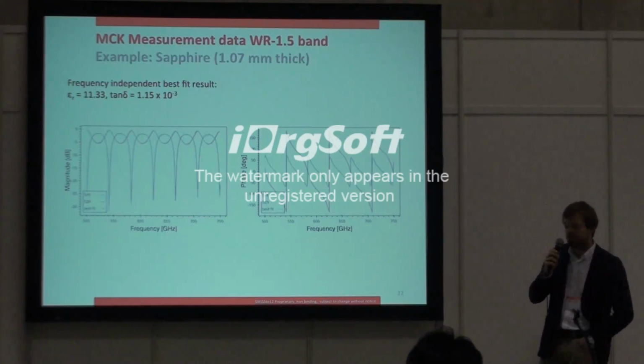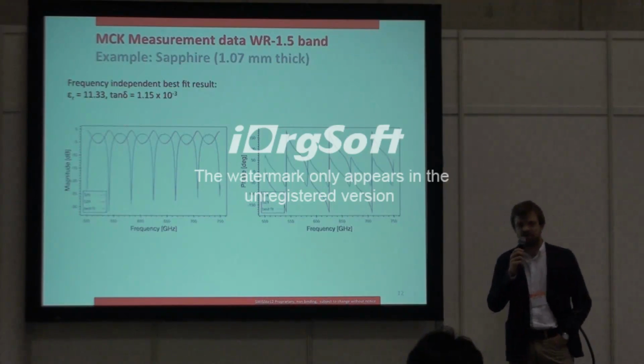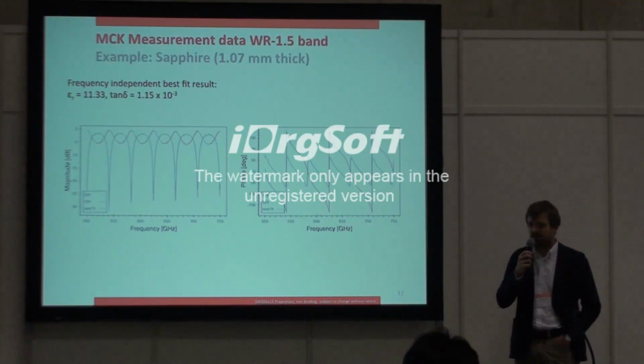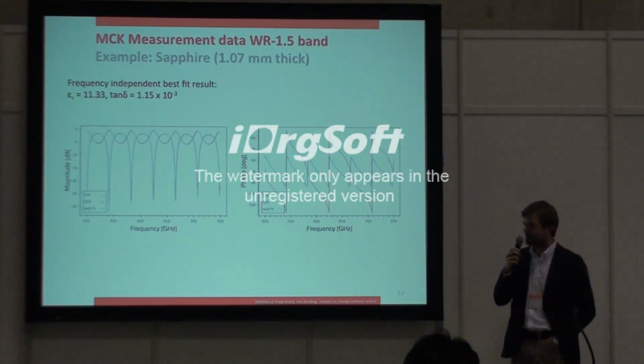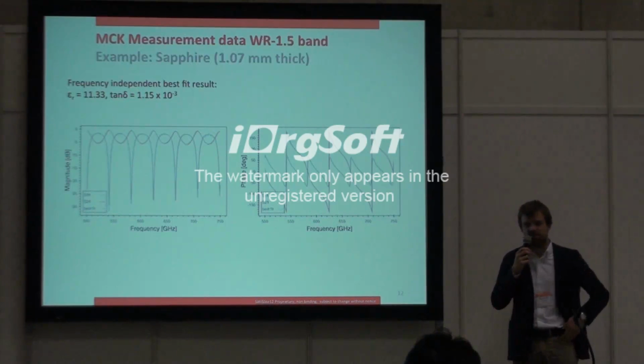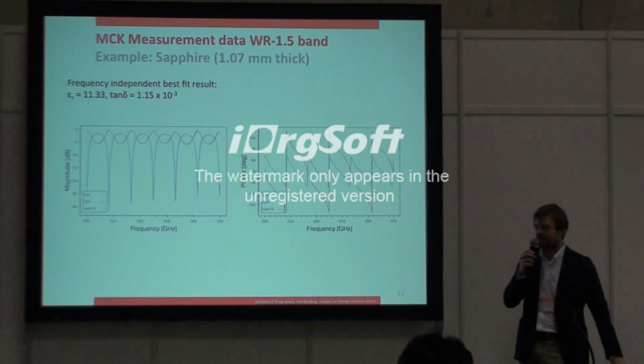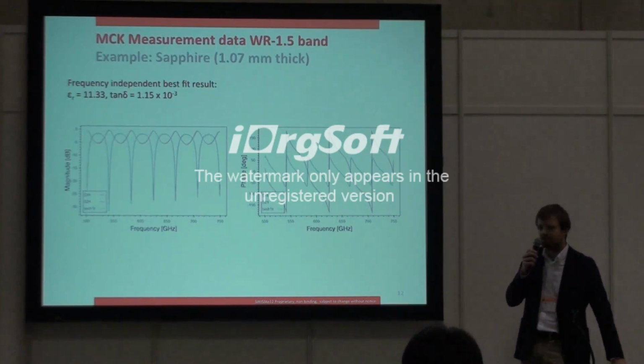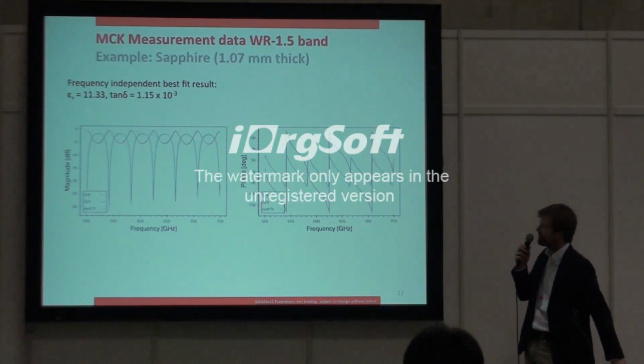What we see is the measurement data, so the blue and the red curves, but we also see a third curve, which we call best fit. The best fit is, in this case, the first data analysis model that we implement in our software. This is a fairly simple model where we assume a constant permittivity of the material over the frequency band. So constant epsilon and constant tan delta over the frequency band. And under that assumption, we try to find the best fit to the data. And we can see here that we have very good agreement between the fitted line and the measured line. So for this material, we have a good data analysis with this model, and we see that we can measure epsilon r of 11.33 and tan delta of about 10 to the minus 3.